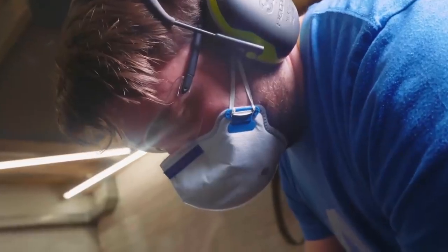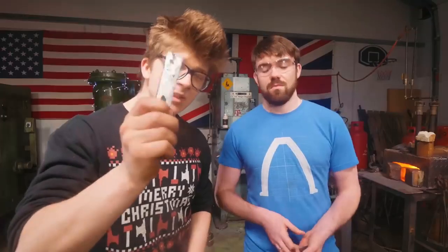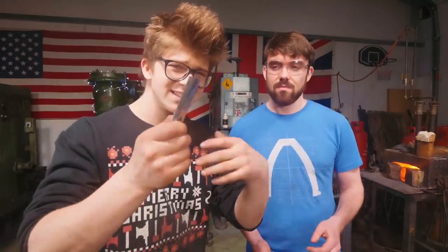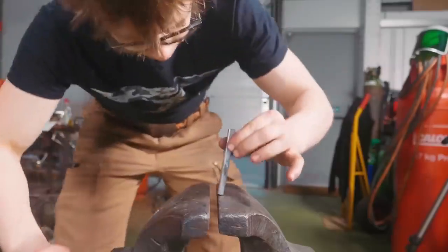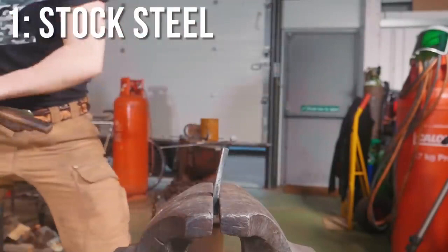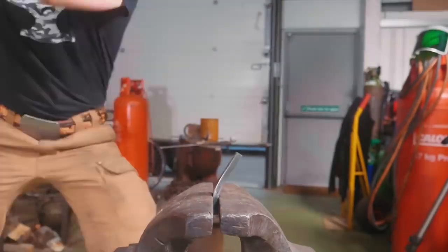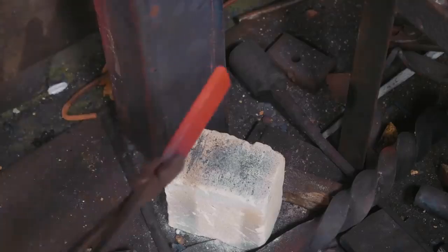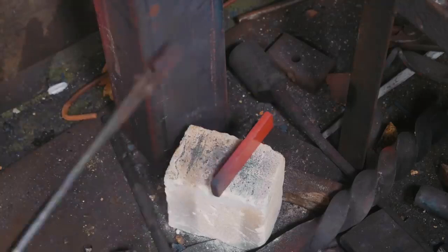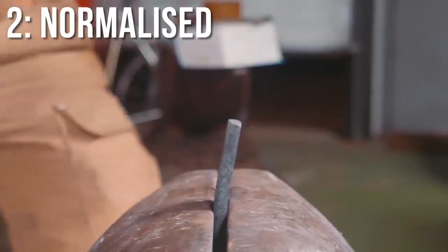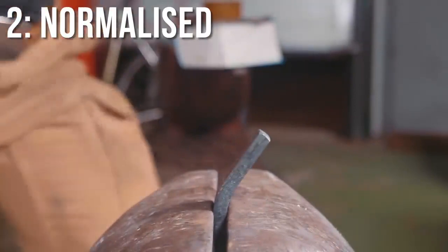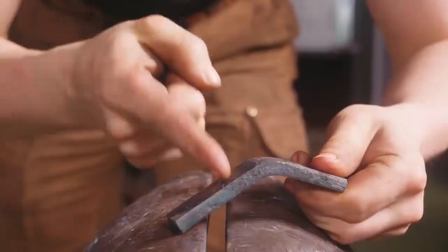To drive home how important this step is, we tested 4 samples of the same material at different stages of the heat treatment process. This was our sample before the heat treatment process, which you will quickly see was the weakest of the bunch. This is the normalized sample, which was ductile with a low yield stress. It took several hammer blows, which it absorbed through plastic deformation, not ideal characteristics for a sword or knife.